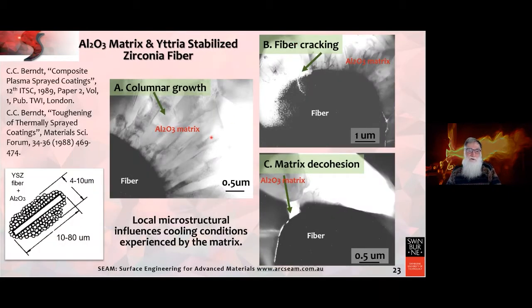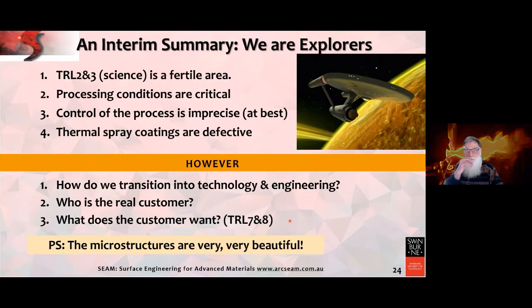Or we could look at composites, and here we have a fibre which is not intended to melt, but the thermal spray material has melted, heat has been conducted away by the fibre, and what we find is oriented growth. But if we do get cracking in these fibres because the heat distortion is too much, that would be bad for this application. And if we get decohesion, that is not necessarily bad because that could lead to increased toughness by strain energy dissipation. So let me give you an interim summary.